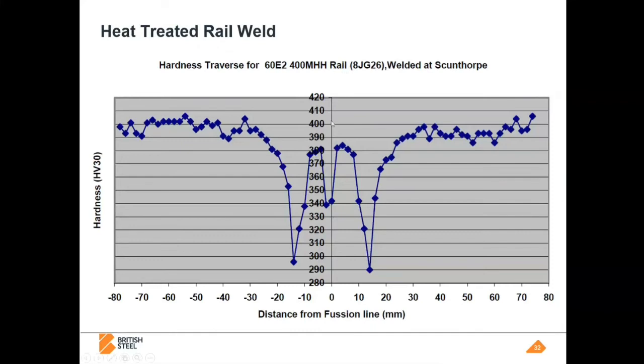on these chromium alloys, the heat treated steels, is lower than the parent. So it doesn't really matter what hardness is at the parent steel. It can be 400 Vickers here. It could be 450 Vickers. It doesn't matter. The maintenance frequencies are going to be determined by the weld, the bit that performs the worst. So it's super important to consider the welding as part of the system. The bulk properties of the rail are irrelevant if you don't get a good weld.